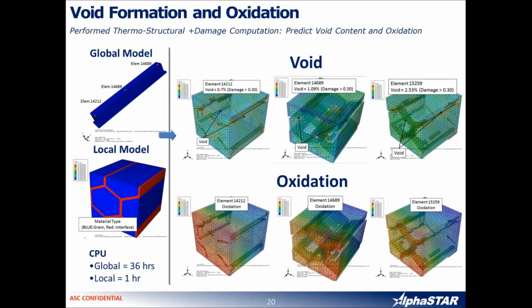On the next slide, which is slide 20, we also look into void formation and oxidation. We perform thermostructural plus damage computation analysis to predict the void content and oxidation. On the left, you see the global model, and we take the global model and break it down into a bunch of local models. As you can see, the CPU time for the analysis for the global can take 36 hours, whereas for the local, if you have a bunch of computers available, you can run them in only 1 hour and get the quick solution right away. And what it provides you is a void for each and every element, and also the oxidation for each and every element. So this becomes very valuable information in our material modeling analysis.